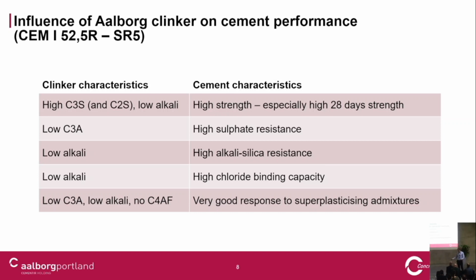You will see that when we compare concrete with our white cement to any other cement, more or less, you can always reduce the amount of superplasticizer needed in your concrete, very often to half the amount. So instead of putting 5 or 6 or 7 kilograms per cubic meter of superplasticizer, you can go down to half and have the same fluidity, the same effect of the superplasticizer.